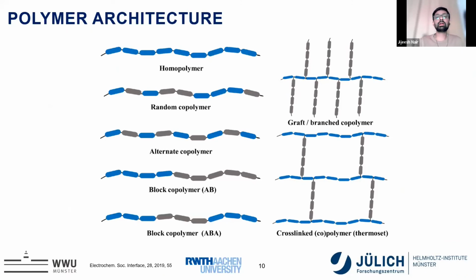Then coming to the polymer architecture, as I mentioned, you may have polyethylene oxide, which is a homopolymer, or you can have a copolymer of PEO plus methyl methacrylate, which is a PEO-PMMA polymer, which could be a random polymer, an alternating copolymer, a block copolymer, PEO block and PMMA block, or polystyrene block, etc., or a tri-block. Or you have a chain which is a polymethacrylate, and you can have a branching or pendant functional group, which is an ethylene oxide chain or other kind of polymer chains. Or even you can have a cross-linked thermoset network. And most of my research work for the last 15 years was focused on cross-linked polymer electrolytes.